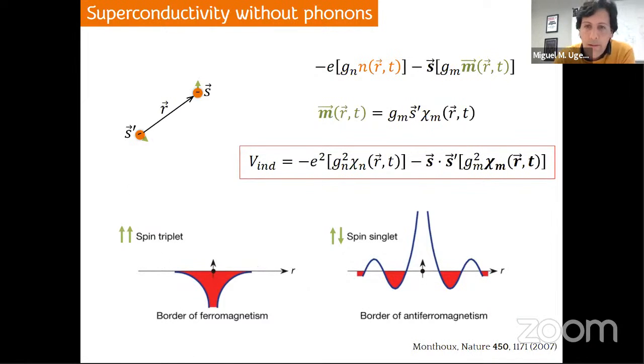In the case of the border of antiferromagnetism, the situation is a bit different, and then singlet configurations are favored, and given the sign of this inner product, basically you have to look at what happens at the magnetic susceptibility. In this case, the magnetic susceptibility in the presence of antiferromagnetism is also maximum, but it does not decay monotonically, but it fluctuates. The sign of the magnetic susceptibility fluctuates, and so does the induced effective potential between these two quasi-particles. So that's why, in principle, spin-spin interactions can mediate superconductivity without the need of phonons.